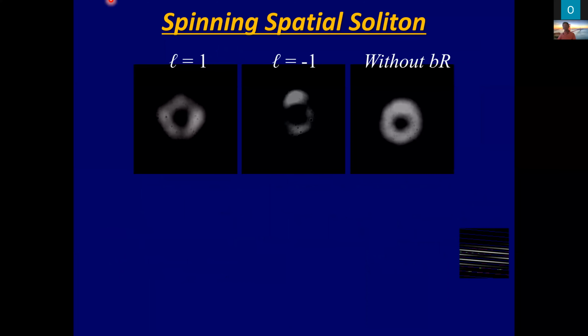You can see that twin mode. The optical vortex, Laguerre-Gaussian mode, passes through the bacteriorhodopsin suspension. At that moment, the Laguerre-Gaussian mode converts to the twin mode. And the twin mode rotates in the clockwise or anti-clockwise direction. This rotational direction is determined by the handedness of the Laguerre-Gaussian mode. Namely, I want to say this is a spinning spatial soliton.